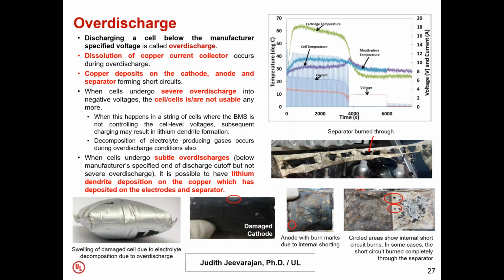Just quickly going into the over discharge, I talked about subtle over discharge and significant extreme over discharge. As you can see from some of our pictures here, there can be decomposition of electrolyte at lower voltages, and in the case of pouch cells, it's very visible with pouch cell swelling. We've seen, with continuous over discharge and recharge, a lot of heat damage in the separator as well as in the cathode and the anode, as you see from the pictures here.